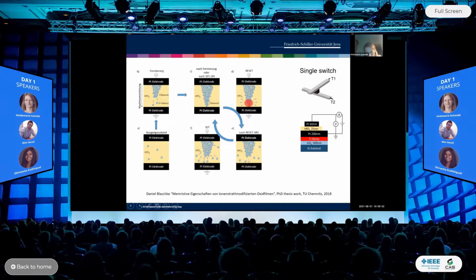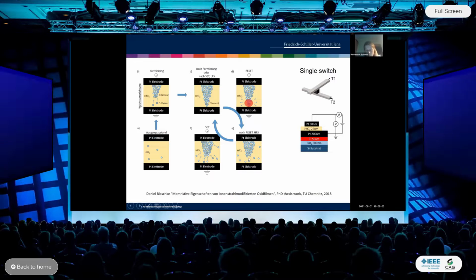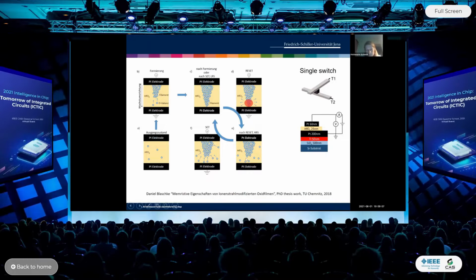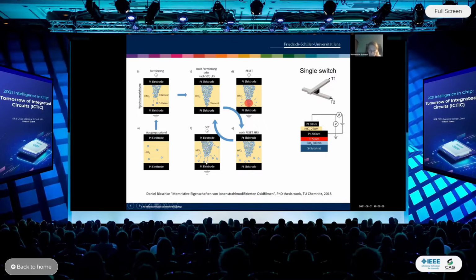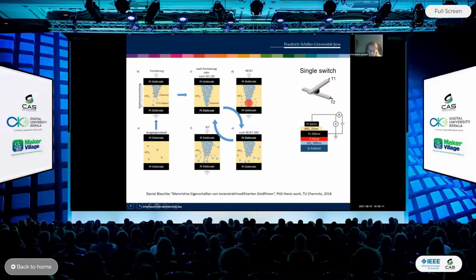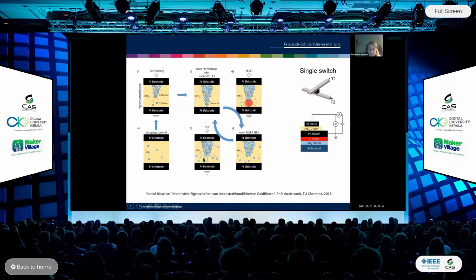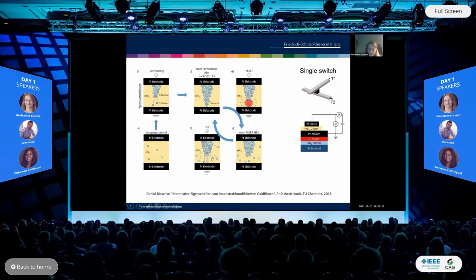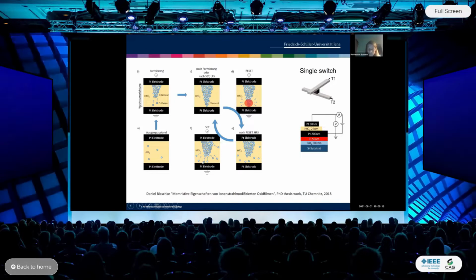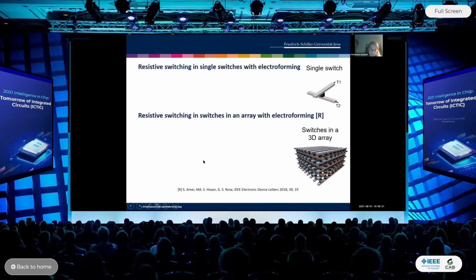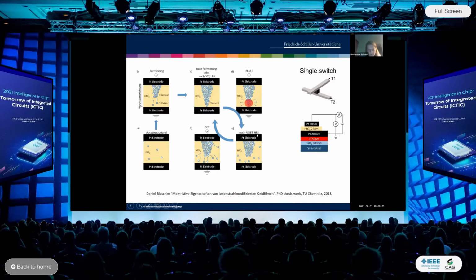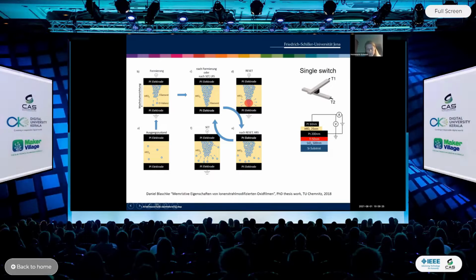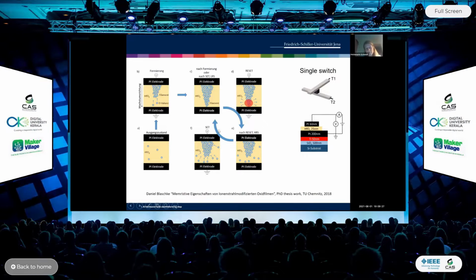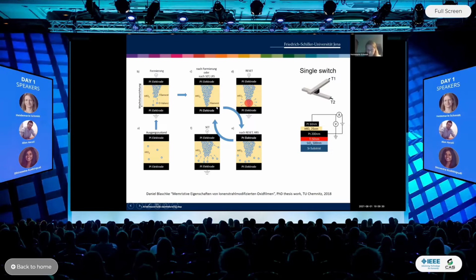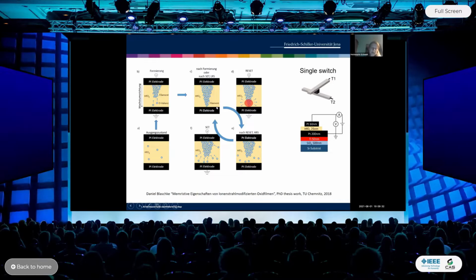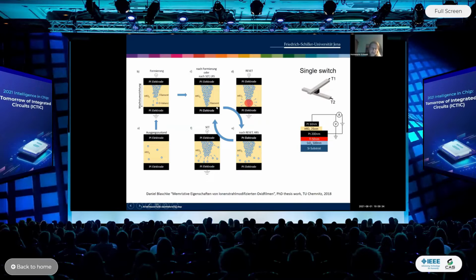But the filament is only broken in a small range, not the whole filament is broken, it's just broken here. And then you make a set process, and here you do not have to bridge such a long distance, it's just a very small distance, and therefore the set bias after the electroforming step and after formation of the first filament is very small. And then you can cycle within those 4 pictures, and you see electroforming is related with the formation of filaments.